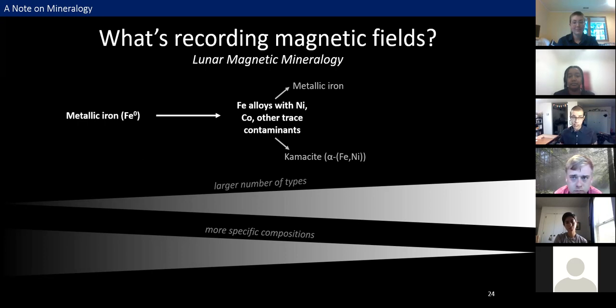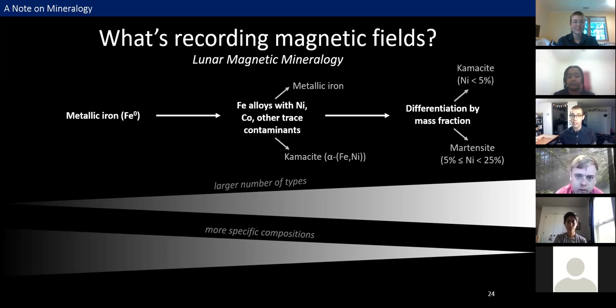Now, over the past decade or so, improved methods for the assessment of paleomagnetic fidelity have been accompanied by more detailed analyses of magnetic carrier minerals, including non-magnetic analyses that let us do things like differentiate iron-nickel alloys by mass fraction. For instance, we can now tell kamacite, which is a low nickel alloy, from martensite, which has a higher nickel content, which is pretty cool.